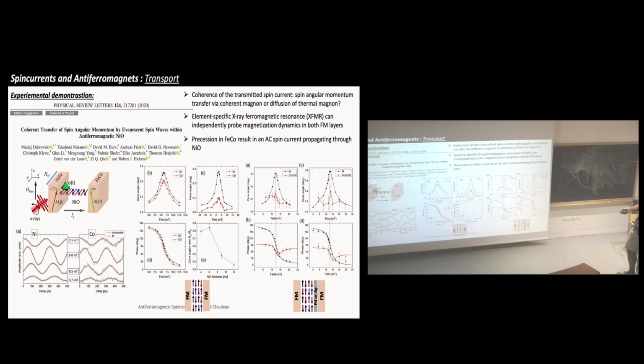They excite this layer at its resonance frequency, and they looked at whether the other one responded at the resonance frequency or something else. They could see clearly that it was responding at the resonance frequency, meaning that you had some kind of AC spin currents at this frequency, as already discussed by Slavin just before. And of course, because they are exchange coupled, you could say something from the ferromagnetic material triggers the NiO, and then since it's also exchange coupled to the other ferromagnetic layer, it is the same.